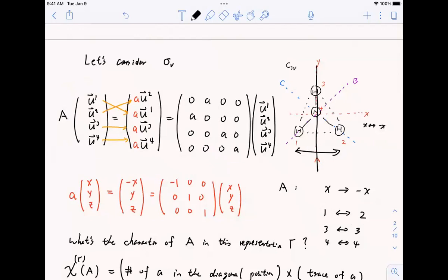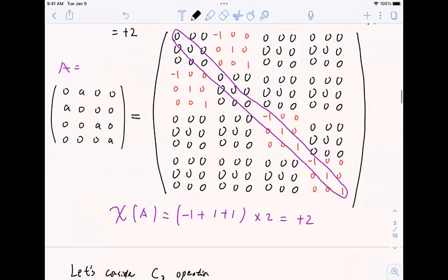You're going to do the same thing for MoS2. But this time, if a Mo atom goes back to a Mo atom, it is the same, even if we go to a different unit cell. So the only difference for the lattice is that when you apply the rotation, if the atom goes to another unit cell but it is the same atom, it is the same. That's the only difference.